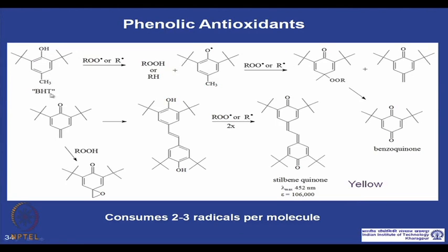For example, this additive traps a radical, forms a radical itself, which can rearrange and react with other radicals and form non-radical species, and these final species like stilbenequinone or benzoquinone are sometimes color bodies.